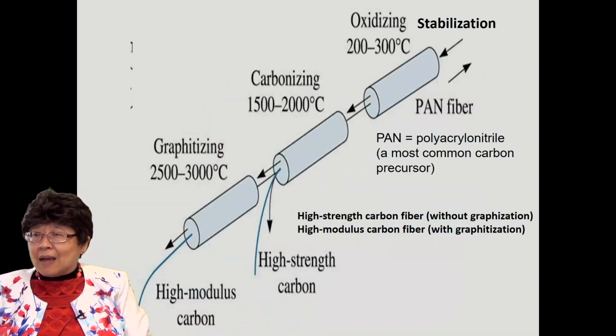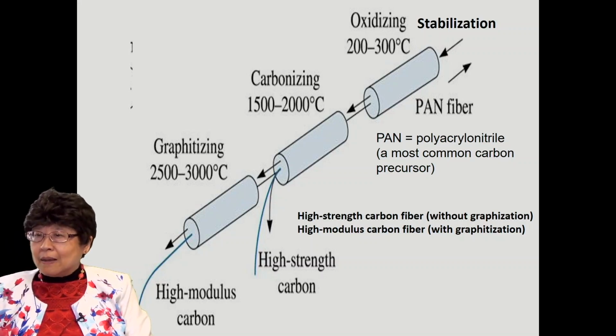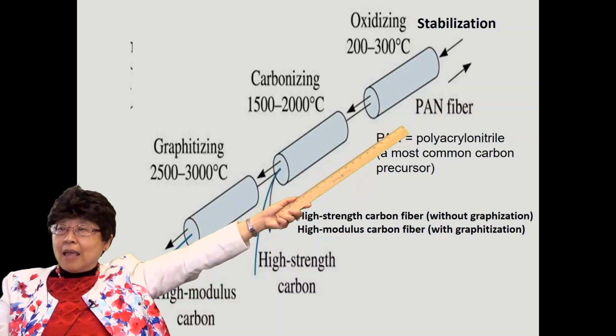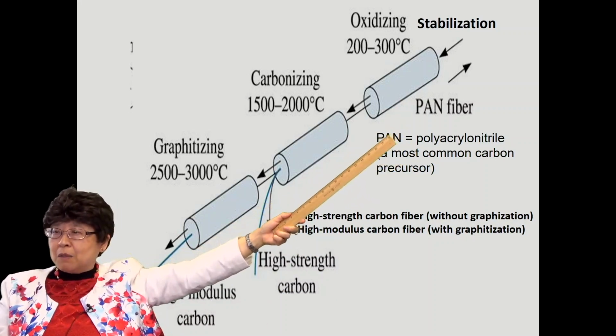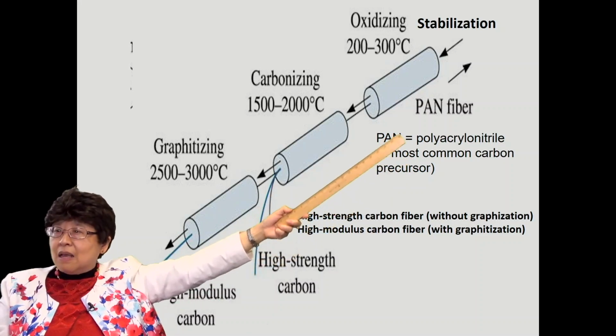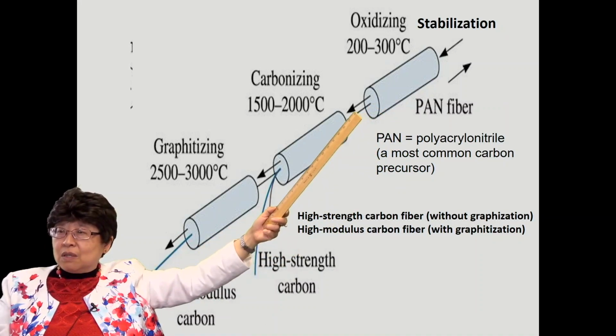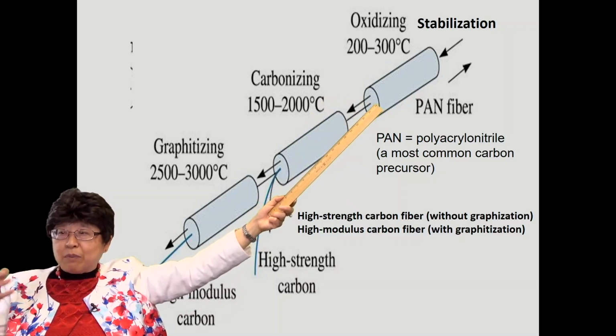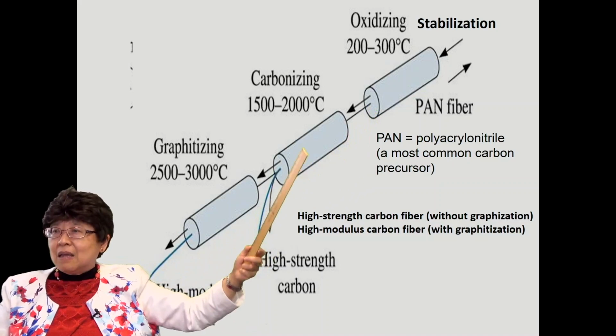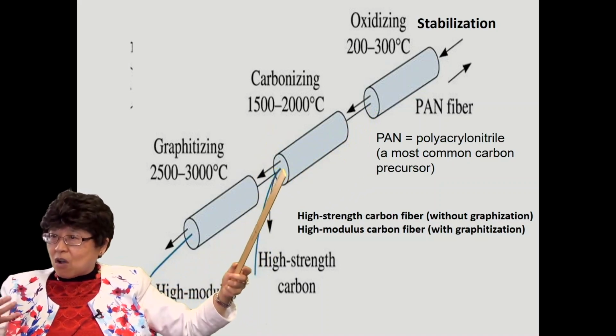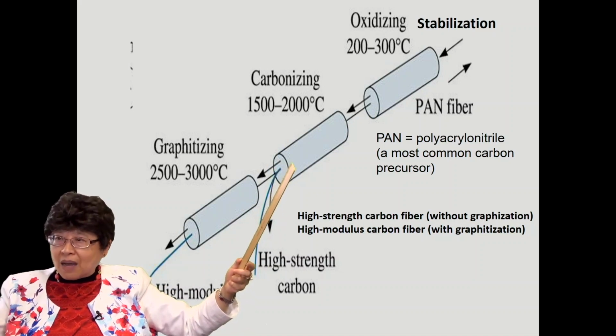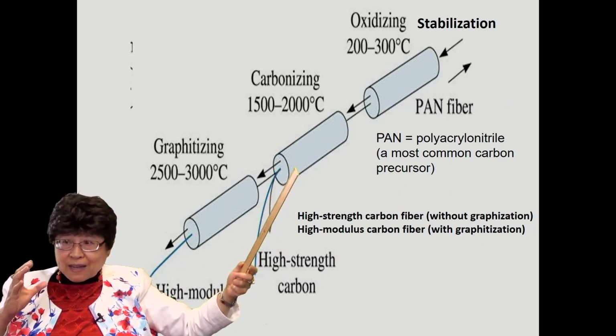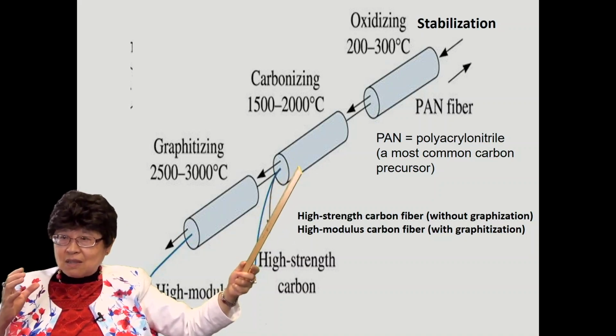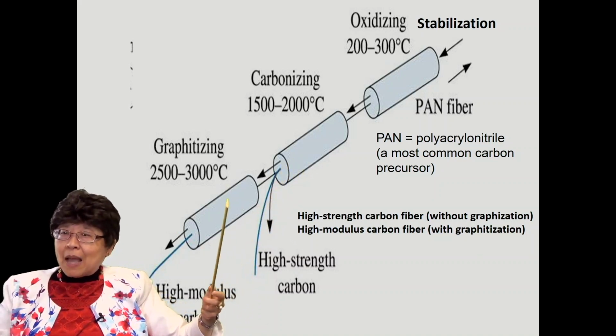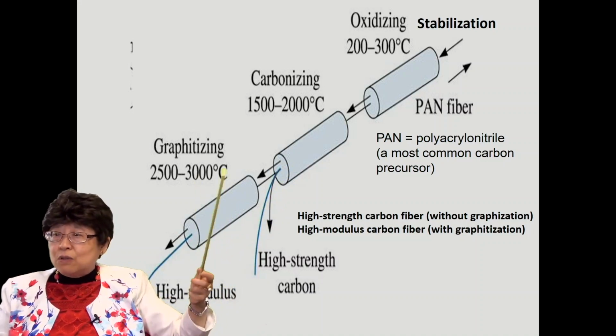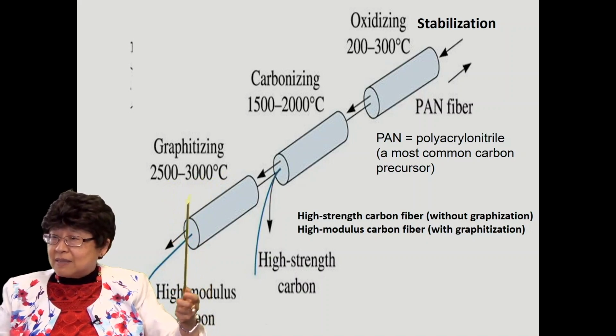Okay. The making of carbon fiber involves typically a polymer fiber. The most common polymer fiber is PAN, polyacrylonitrile, and it's subjected to oxidation at a low temperature so that it wouldn't melt upon subsequent heating. And then it's subjected to carbonization so as to convert the polymer to carbon. But it's not graphite yet, not the ideal graphite yet. It's just carbon. And then if you want it to become graphite, then you have to follow that with a higher temperature heating, the graphitization process.